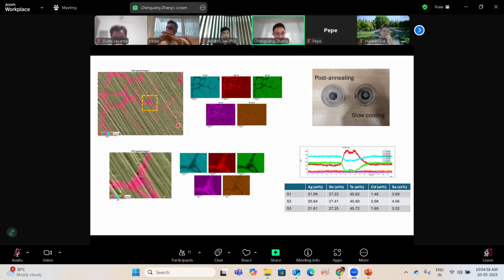For the post-annealing samples, I did a line scan. Actually, I zoomed in, and it's almost like what we captured before. Then I drew a line scan in the SEM-EDX, and you might see the selenium and the cadmium distribution, the orange and the purple line, is almost uniform, more than before, I think. You can also see the selenium here, and it's very homogeneous, at least from what we can see, or we cannot tell at such a scale. But you'll see later that it's quite different from the slow cooling sample.